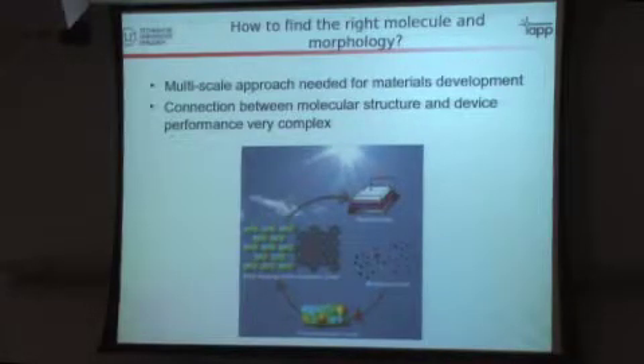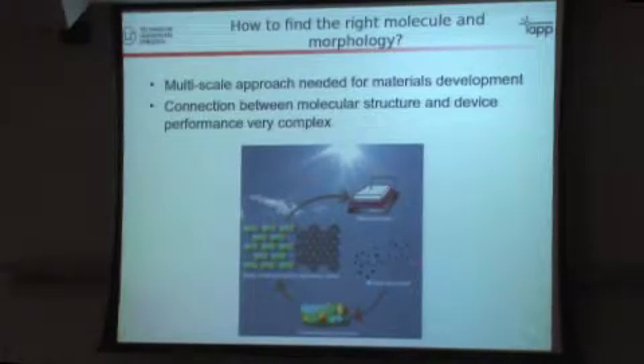But the key challenge at the moment is that ideally we would define a solar cell by designing a high efficiency device, and then we would go this way. We would go back and tell the synthetic chemist, please make this and this molecule to have the right properties. At the moment we go the other way. We make a molecule, go all this way, and then we judge the quality of the molecule. And I'll show you later in my talk that going this way is very difficult, because the device you get at the end depends not only on the molecular structure, but also in much detail on how you process the devices and what the conditions are.